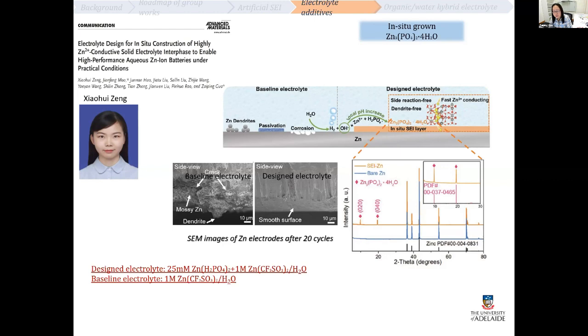So to in situ grow a stable, passive, effective SEI on the surface of the zinc anode, we need to add some additives. So in this case, we add zinc dihydrogen phosphate as an electrolyte additive. It could react with the OH group released from the corrosion reaction in the very beginning, then form this zinc phosphate. This zinc phosphate will deposit on the zinc anode, acting as the in situ SEI layer.